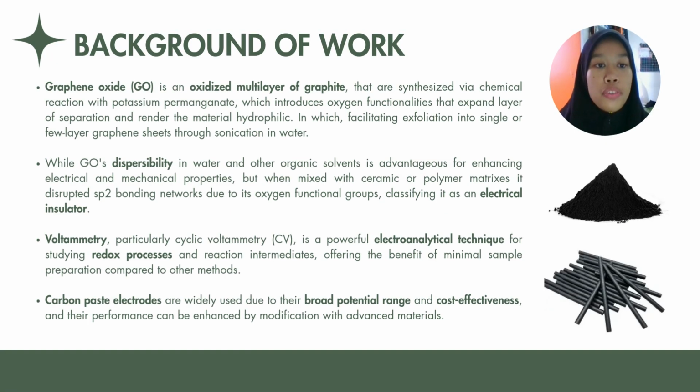Moving on to the background of the work, graphene oxide (GO) is an oxidized multilayer of graphites that are synthesized via chemical reaction with potassium permanganate, which introduces oxygen functionality that expands layer separation and renders the material hydrophilic, facilitating the exfoliation into single or multi-layer graphene sheets through sonication in water.